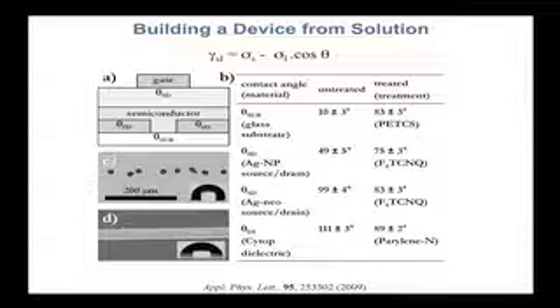Best dielectric materials deposited from solution are very hydrophobic materials. Basically, Teflon is an excellent gate dielectric. Cytop is an excellent gate dielectric, but they are very hydrophobic. So again, if I want to print the silver on top of that material, I'll just get isolated drops that are de-wetted, and I'll not get this nice line that I need as a gate. So you change one material, you have to characterize everything again. You change the substrate, you characterize everything again. And that's how printed electronics works. It's very easy.